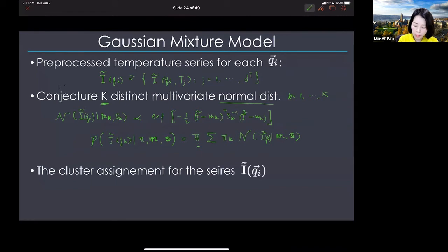And then the machine learning task is to figure out what is the optimal weight, means and variances that best describe the data. We are just trying to learn the best way to describe the data. And once we learn these hyperparameters, so-called, through the expectation maximization algorithm, we have a cluster assignment for each reciprocal space point, given by the weight associated with that point Q of I: the likelihood of that Q of I belonging to a cluster K, given by the weight for that cluster K and the learned normal distribution, and normalized. So it's really simple.